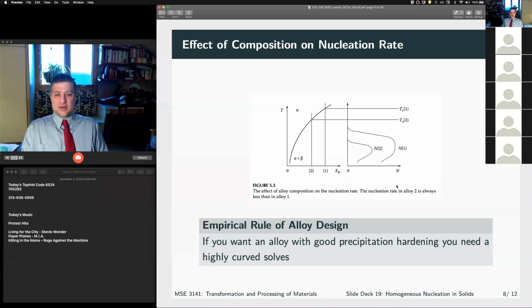Okay, so that brings up an empirical rule for alloy design, right? Which is, if you want an alloy that has good precipitation hardening, you want a very sharply curved solvus line, right? If this goes up just a little bit, it's very difficult for me to get these large supersaturations and large undercoolings necessary to get high nucleation rates, right? We'll see this in aluminum in just a little bit, right? If I want a uniform dispersion of precipitates, I need easy nucleation. If I only have a little bit of nucleation, I'm going to have very few particles that are going to grow large. If I want lots of small particles, secondary phase particles, I need to enhance my nucleation, right?